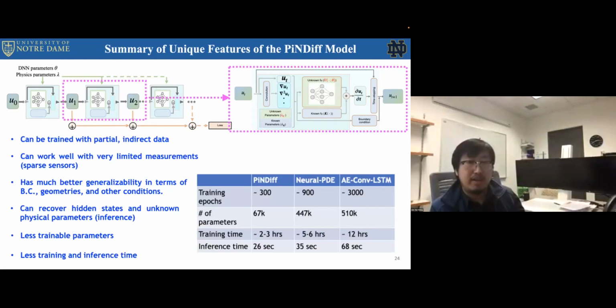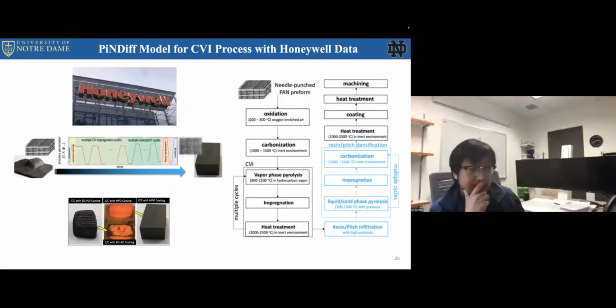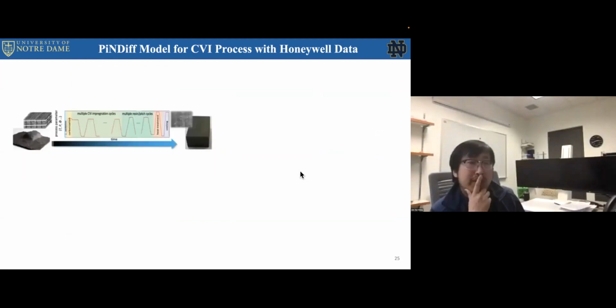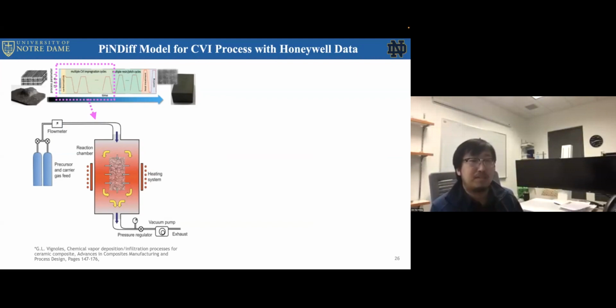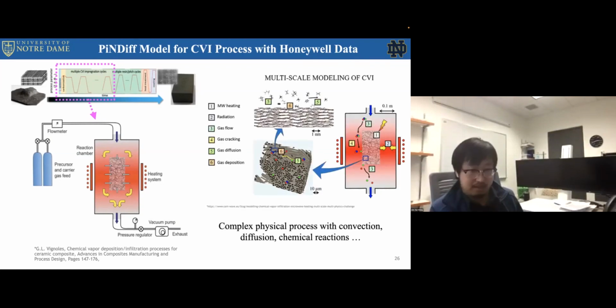So that's pretty great. We would like to move forward and think about how we can integrate the real data from Honeywell, from the real manufacturing process. Here I'm going to show you a different process involved in this carbon-carbon composite manufacturing. In Honeywell's recipe, chemical vapor infiltration is a very important process, and they will do these CVI cycles many times to densify the carbon composite from the porous preform, so they will deposit carbon. This process involves chemical reactions in an oven, and they provide reactive gas, and you have the preform, and with the chemical reaction, they deposit carbon and densify the porous preform.